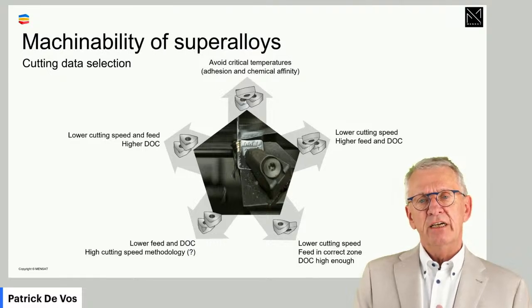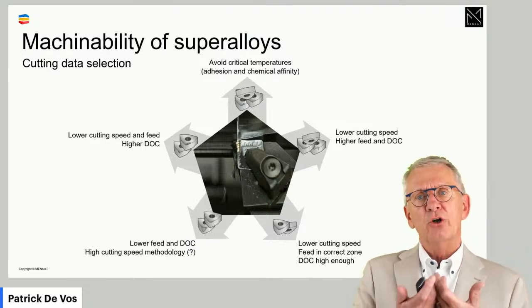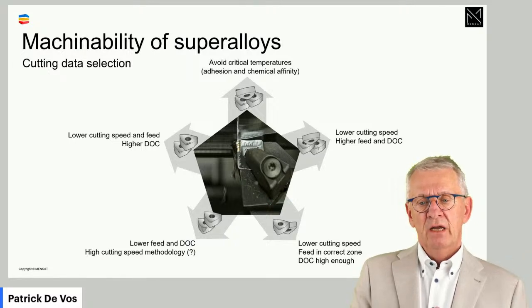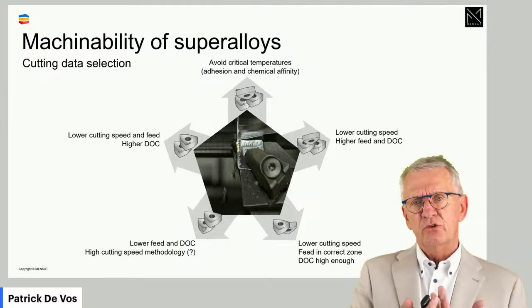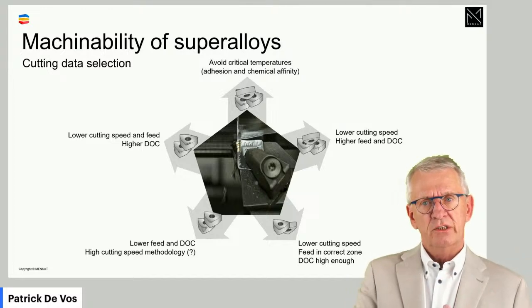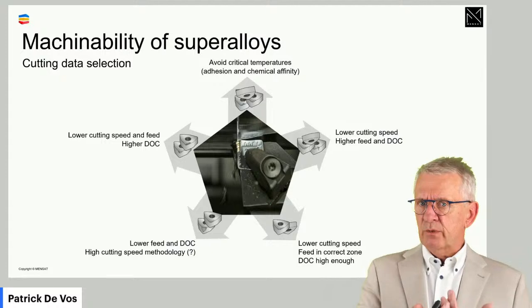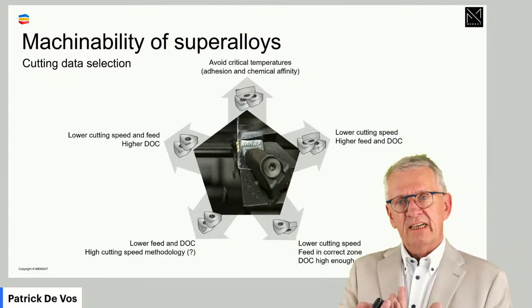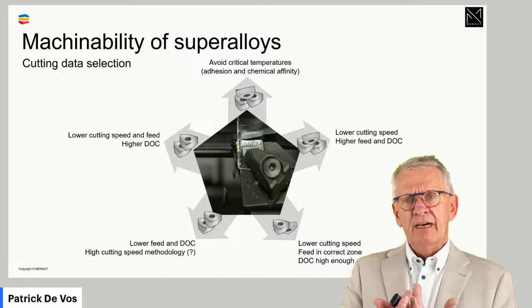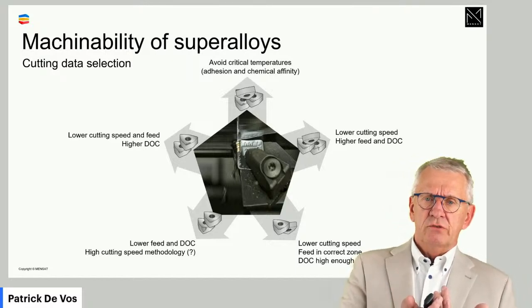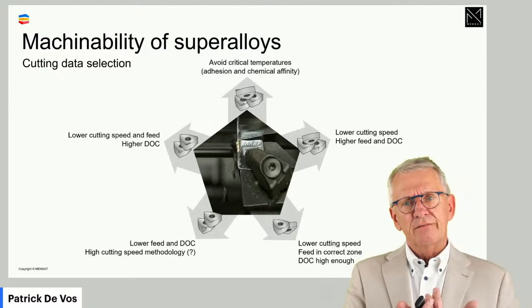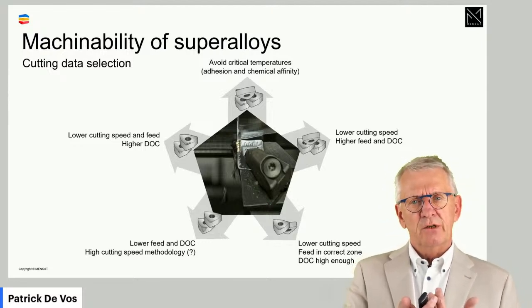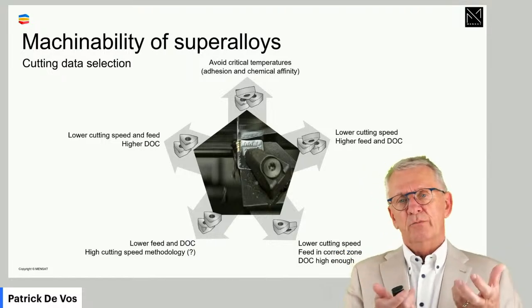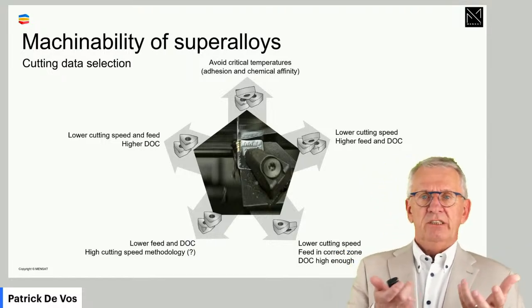Because whatever, if a certain property is the predominant property you want to tackle, let's say it's strain hardening, like we have in superalloys. Strain hardening means that your tools need to be selected first based on the geometry. We need sharp geometries. The carbide grades have to support that sharp geometry. And the cutting conditions, you should use lower cutting speeds and higher feeds, and depths of cut you should be a bit careful with. And you do all of that and you start machining and then you ask: is this now the best? Did I do well?